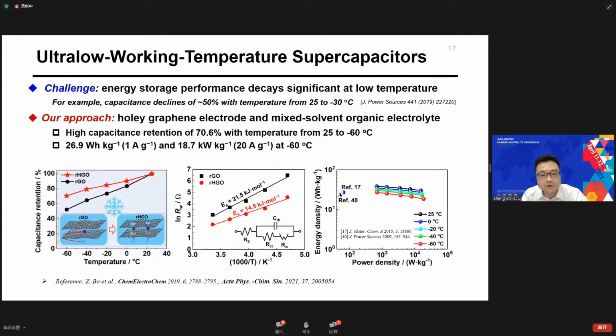Supercapacitors with low working temperature have become highly desirable. However, the energy storage performance declines significantly at low temperature. For example, the capacitance decay of up to half can be observed with working temperature decrease from 25 to minus 30 Celsius degrees. So our work achieves ultra-low temperature supercapacitors based on holey graphene and mixed solvent organic electrolytes.